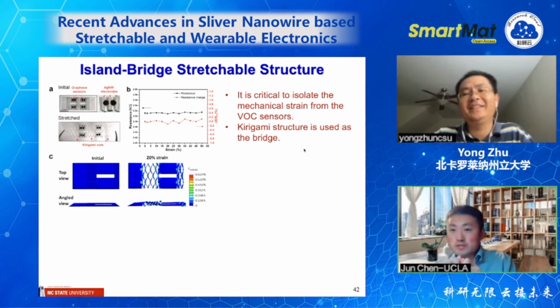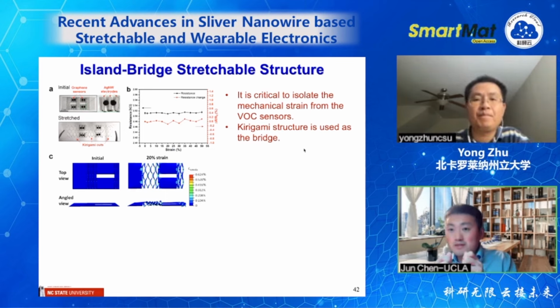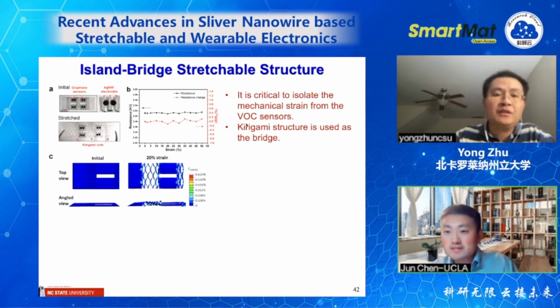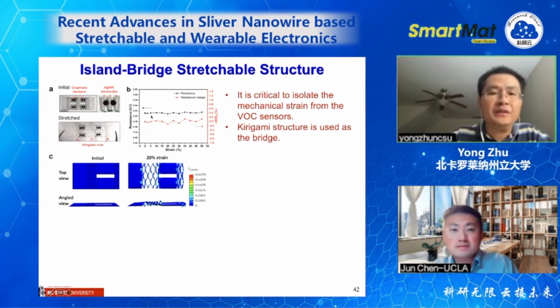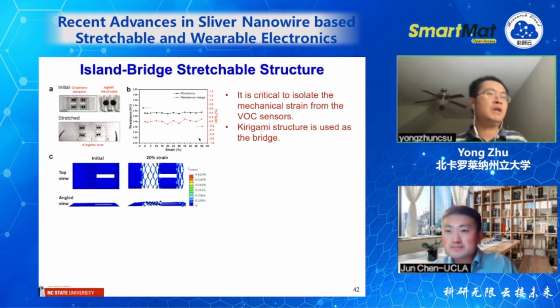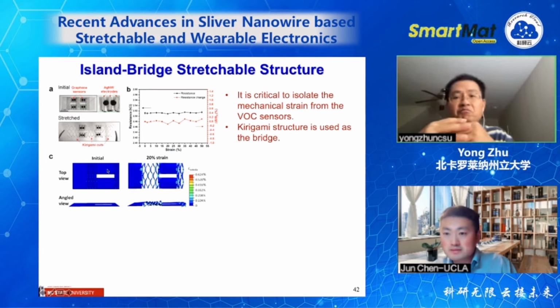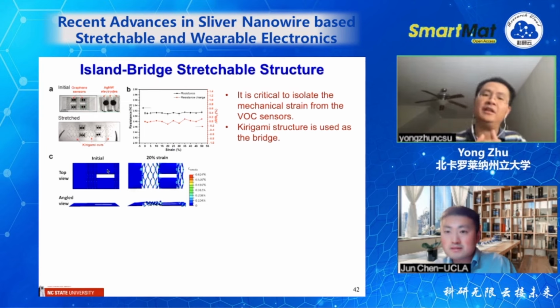So how about the stretchability? If we stretch a device, does the contact resistance change? I don't think so, because we don't know the contact resistance itself. What we measure is the total resistance, and you can see it has almost no change up to 50%. I think it is okay, because the major factor is this kirigami structure. The contact has minimal strain on it. I think that is the key, and it contributes to this almost constant resistance.